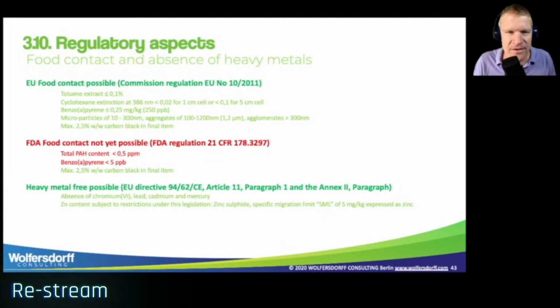The specification is in this slide. So the toluene extract needs to be smaller than 0.1%. The cyclohexane extinction at 386 nanometers needs to be below 0.02 for the 1 centimeter cell or below 0.1 for the 5 centimeter cell. Benzo[a]pyrene, the most nasty compound of the polycyclic aromatic hydrocarbons, needs to be below 0.25 ppm, milligram per kilogram, or 250 parts per billion.